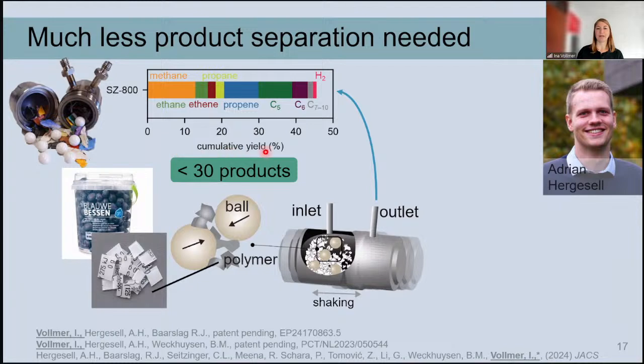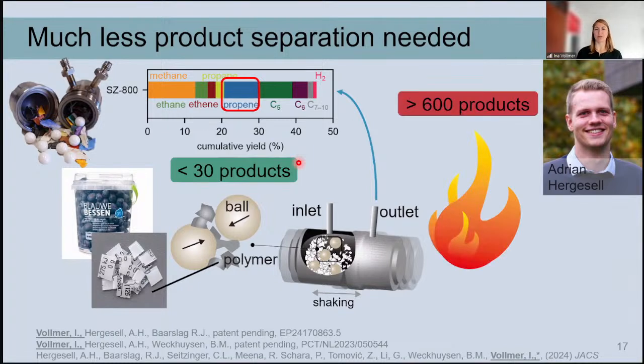So when we really optimize the conditions, we can also already convert around half of the solid plastic to gas phase products in 1 hour. And you can see that the different products, they are around 30 different ones, a little bit less. And this is, of course, in stark contrast to what we get from pyrolysis with thousands of different products obtained there. And because there's a significant amount of propene in this gas phase stream, it also could make sense to actually separate these different products and to obtain the monomer from this process directly. It's a little bit similar to a steam cracker output, actually.